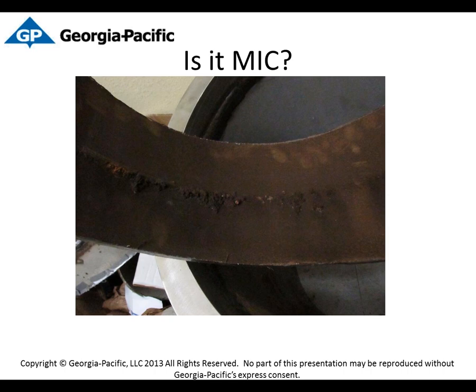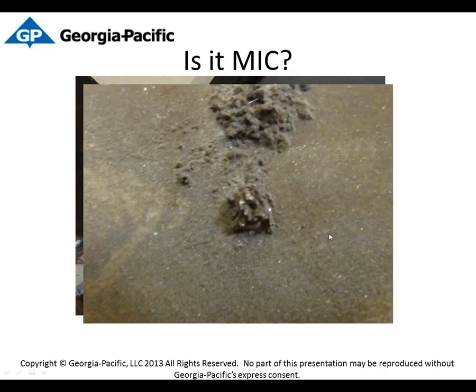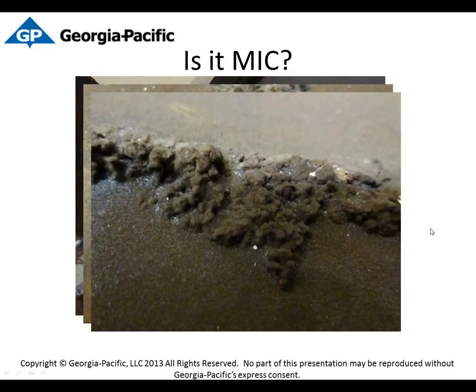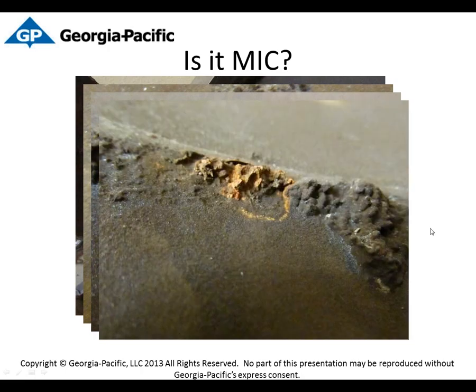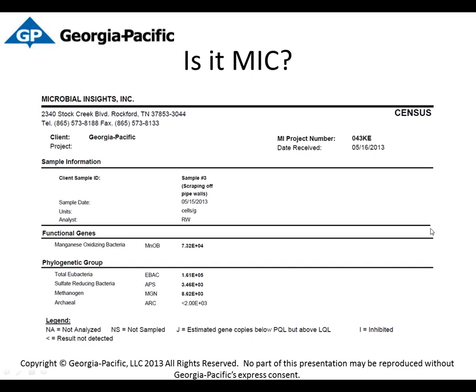So it wasn't until about 6 months later, after we first noticed the corrosion on the bottom side of the piping, that we were actually able to pull a sample out of that hot water piping. And this is what we found. Actually, tubercles were going all along the bottom of the piping. And here are closer-up pictures of what they looked like. So at this point in time, we're still not 100% sure if we had MIC